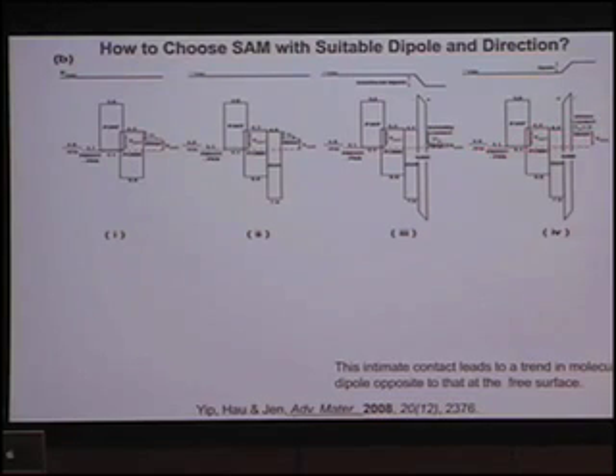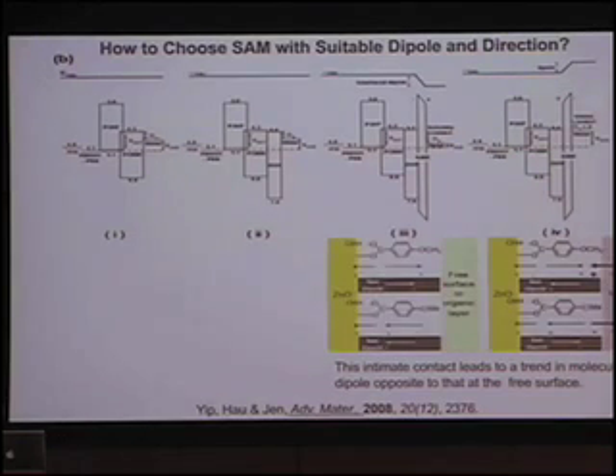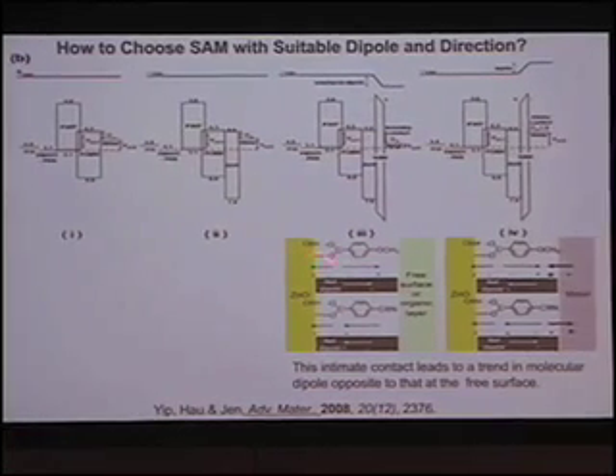Okay, as a result, you can have much larger open circuit voltage of your devices. So if you look at this slide to further explain that. When you have a SAM formed on zinc oxide, when you have carboxylate here, you form a small dipole pointing toward the zinc oxide direction. However, this molecule has its intrinsic dipole pointing in this direction, and it is larger. So the net dipole actually points toward the free space. Vice versa for an electron withdrawing substituent molecule, then you have a net dipole pointing in this direction.